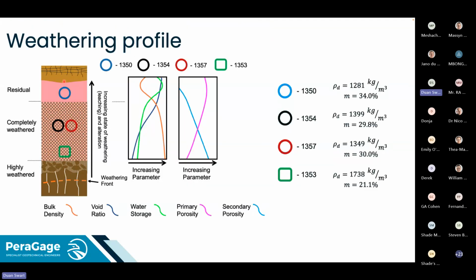If we take that data, and other data from tests I can't cover here, and put it back into the weathering profile, you have your sample locations and this increase in the state of weathering. You will then have these different vertical structural profiles. If you follow with me, generally bulk density starts at a certain point and decreases, carrying on decreasing through the residual. But at some point in the residual, it will be too voided and will collapse on itself, compacting, and you get an increase in bulk density. Just for interest's sake, that's typically where your ferrocretes form, because as the water comes through the topsoil or the transported soil, it hits that densified layer and then flows laterally, and that is where ferrocretes like to form, with that sitting water.